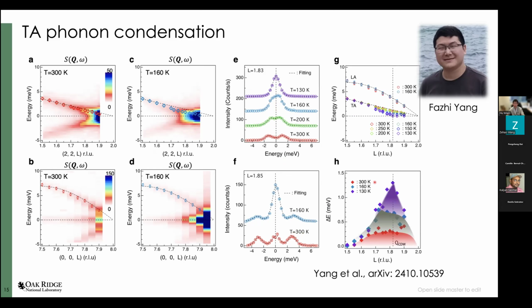So these panels summarize what we observed. Indeed, the longitudinal acoustic phonon doesn't respond to the CDW, but the transverse acoustic phonon shows a Kohn anomaly. If you remember what I just showed you before for the schematics, these observations really prove that for europium aluminum 4, the CDW is a transverse Peierls transition.